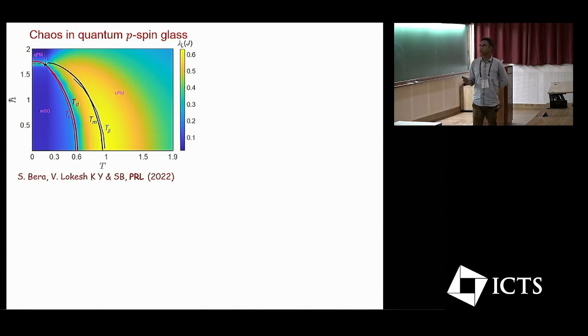This is a model which I'll describe very briefly later. Basically this is a quantum spin glass model which is called a quantum P spin glass. What is plotted here is a chaos phase diagram as a function of the quantum parameter and temperature, and what is plotted here is the Lyapunov exponent calculated in some way. And what you find is that there is this glass transition temperature. So this model has an exact thermodynamic glass transition and a dynamical transition at Tc and Td.